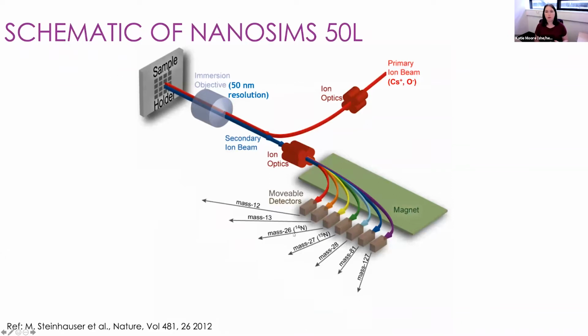Here we have a very simple schematic of the NanoSIMS and how it's laid out. On the NanoSIMS, we have two primary ion beams, a cesium plus ion beam and an oxygen minus ion beam, which we use to focus down onto our sample surface. As I said, we scan that primary ion beam over the sample, generating those secondary ions which we want to look at. We extract those secondary ions through a series of optics, and then they enter a very large magnet, into a magnetic field. That magnetic field separates out the secondary ions according to their mass. The magnetic field will affect lighter elements more strongly and heavier elements less strongly. That's how we can separate out all these ions as they come off our sample.